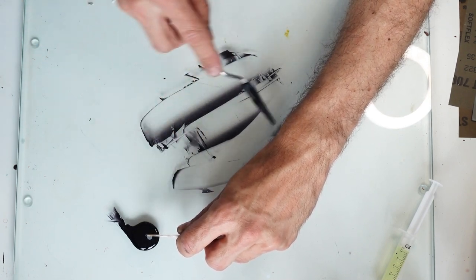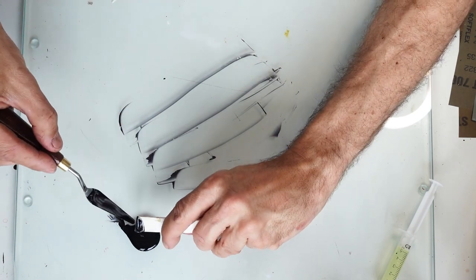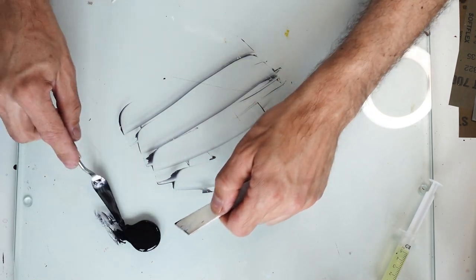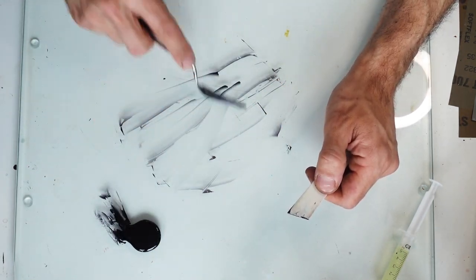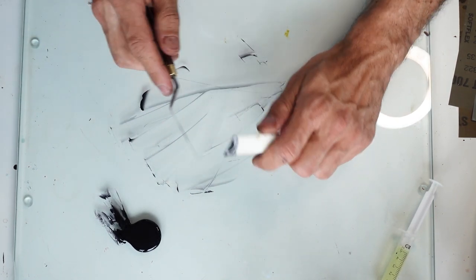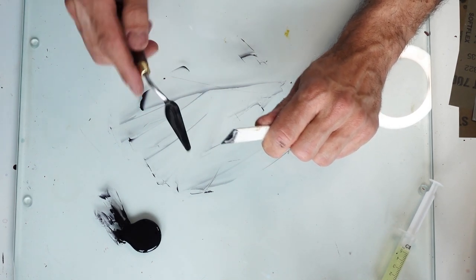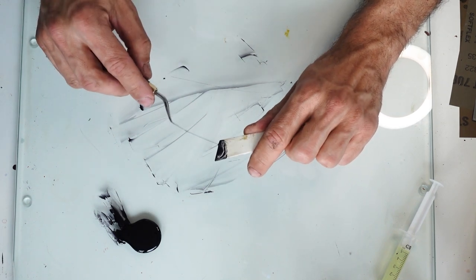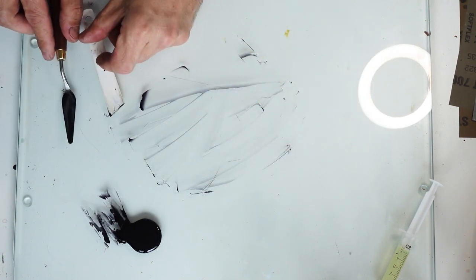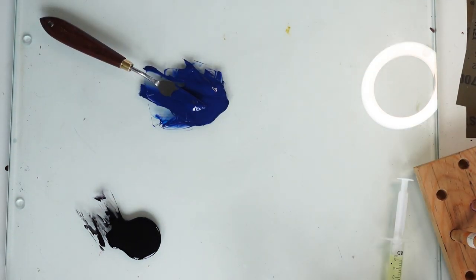But to slow this process down, you have to cure it in lower humidity, so below 70%, definitely below 70%, and much longer. For thin layers, and in case of Kara-nuri, thin is between 0.2 and half a millimeter, and it should be at least a week. And for thicker layers, up to 2 millimeters, because it's possible to apply 2 millimeter layers with such additives, up to 3 weeks.